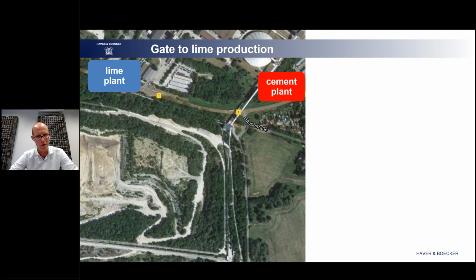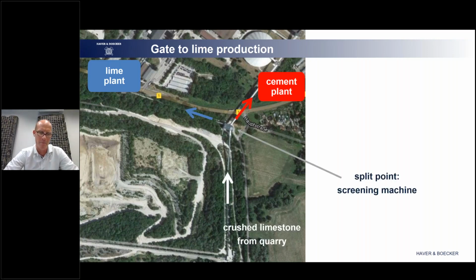It is a common quarry used for a cement plant and a lime plant. And when we follow from the below left corner the way of the belt conveyors, we see one splitting point, which is here a screening machine dividing the coarse material to the left, following the blue path, to the lime plant, and bringing the finer fraction to the cement plant. So obviously here in our cement works, combined cement and lime plants, this is working well already.